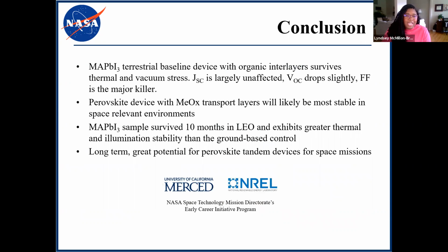So to conclude today, I'd like to remind you of the key takeaways. We have a MAPI terrestrial baseline device with organic inner layers, and it survived a thermal vacuum stress. The results from that was the short circuit current was largely unaffected. Our open circuit voltage dropped slightly, and the fill factor really was the major killer. And from that, we could conclude that our perovskite devices with the metal oxide transport layers will likely be most stable in space relevant environments. So we're working on developing those.